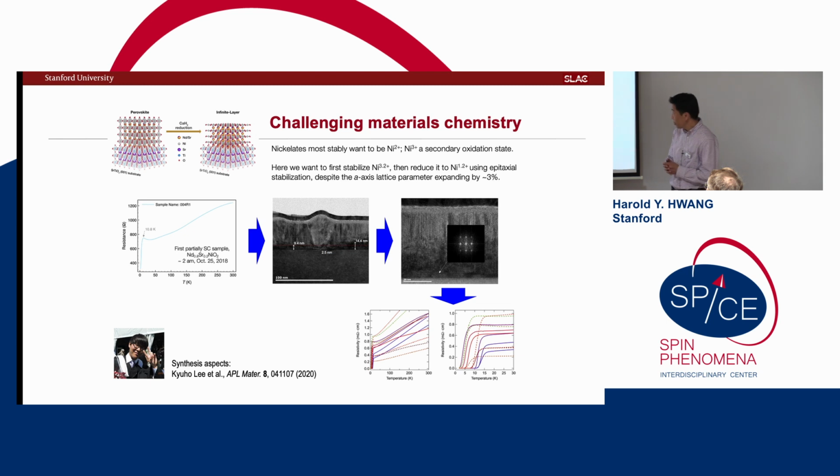So just to talk to you through the kind of materials challenges, this series of kind of chemistry reduction reactions requires you, in this particular case, to go to a very high, unusually high oxidation state of nickel, then reduce it to a very low oxidation state of nickel. And all the while, we're trying to keep this oriented on a substrate. And so this lattice constant is moving around by a few percent. Right? So that's the opportunity and challenge.